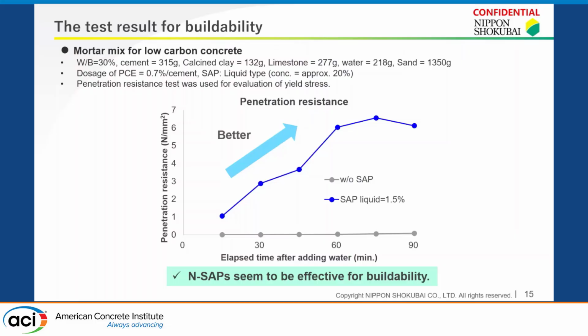This slide presents the test result for buildability with a mortar mix designed for low carbon concrete. We used N-SAP as a liquid type, expecting its application for a two-component system in 3D concrete printing, which has a secondary mixing process just before extrusion. And we evaluated buildability by measuring yield stress of the mortar mix through a penetration resistance test.